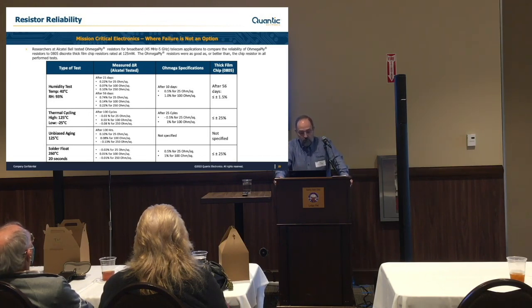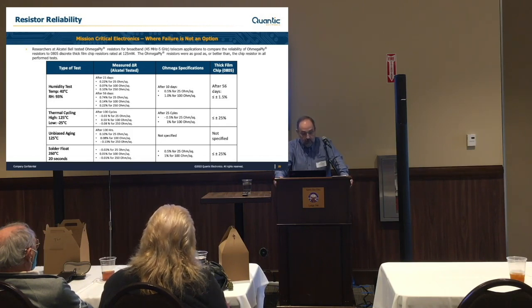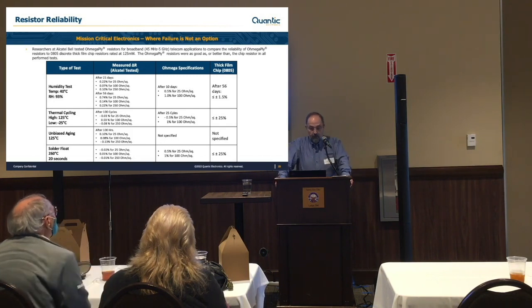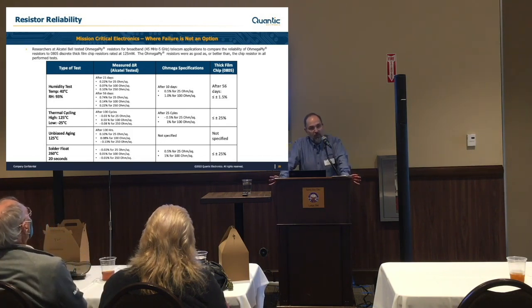In fact, thick film usually changes a bit more than our material does. Thermal cycling, again, we've seen very little percentage change, going from 125 to -25 degrees C, and you get very little shift in the ohmic values. And then we've done both unbiased and biased aging. After 100 hours, you can see we got very little shift. And this is all verified. This is not by us. Alcatel did a lot of the initial testing on this stuff.